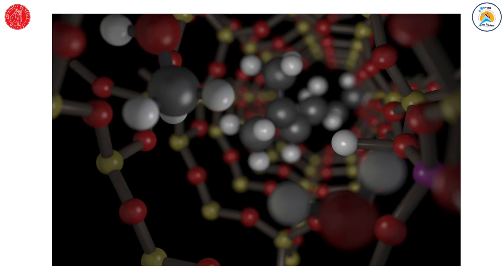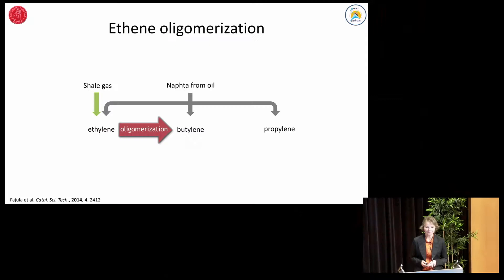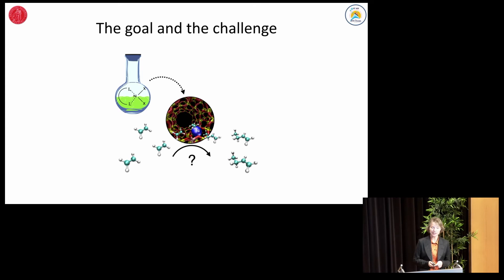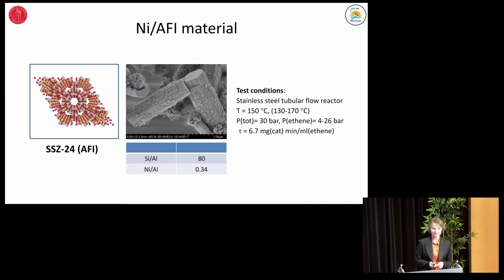TAP reactor conditions are far from those encountered under conventional reaction conditions. As will be seen from our next example, even intermolecular interactions in zeolite pores may now be captured by computational models. We selected a simpler reaction system — ethylene oligomerization. Ethylene oligomerization has received increased attention after the shift from naphtha to shale gas as cracker feedstock, as an alternative route to butene and propene formation. Industrially, ethylene oligomerization is carried out over homogeneous nickel complex catalysts, and there has been a drive towards developing heterogeneous catalysts. Nickel-containing zeolites are among the studied systems, and a clear correlation has been found between divalent nickel ions exchanged onto Brønsted acid sites and activity for the ethylene oligomerization reaction.